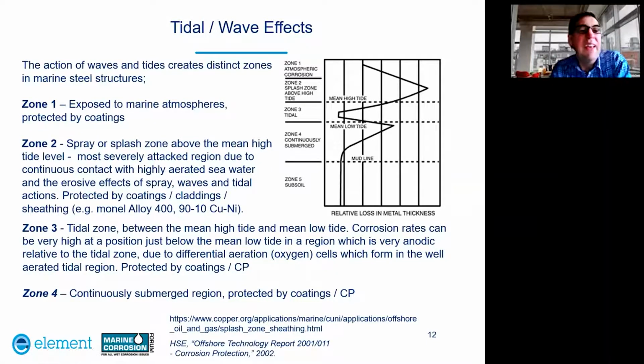Zone 1 is exposed to marine atmospheres, so steels in this region would be protected by coatings. Zone 2 is a spray or splash zone above the mean high tide level. This would be the most severely attacked region due to continuous contact with highly aerated seawater and the erosive effect of spray, waves and tidal actions. This region would need to be protected by coatings and at times by claddings and sheathings. Monel 400 and also 90/10 copper nickel have been used as sheathings to protect steel in this region.